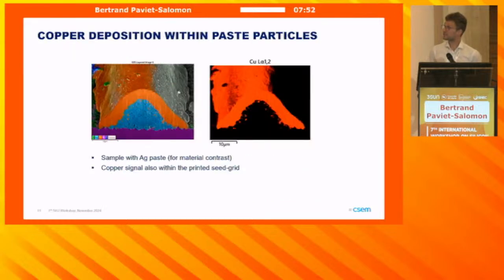Here are some cross sections of the lines after plating. You can recognize on the picture on the left that the bulk part is the seed grid. In that case, it was made out of pure silver, but it can also be made out of something else. And then it is tightly surrounded by the copper cladding here. Something interesting which we actually reported already in the past is that, as you can see on the right, we have the copper metal penetrating pretty tightly into the seed grid, which is beneficial both for the mechanical stability of the contact and also for its electrical property.